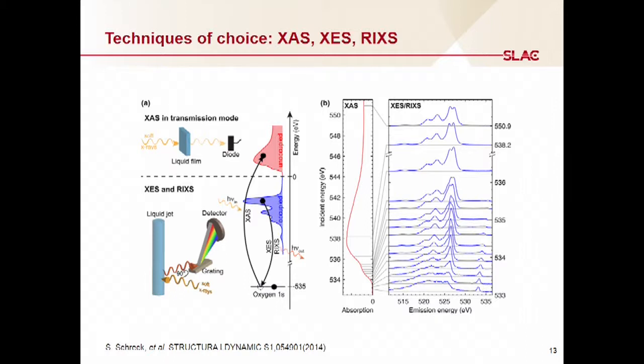And by changing the incoming energy, we can see what gets transmitted to the sample, and this gives us the X-ray absorption spectrum. At the same time, if there is a means to track the energy of the photons that come out, the electrons that fill that empty state here, we can get X-ray emission spectroscopy. And this really tells us a lot about the occupied density of states. And in order to do this, we need to have a grating spectrometer. For the soft X-ray regime, this is by far the method of choice, to disperse the beam and send it to a detector and measure each color individually.